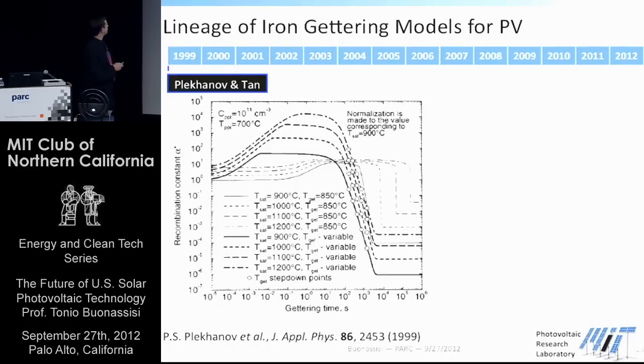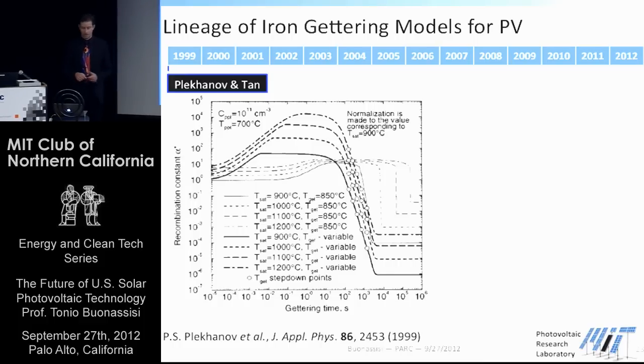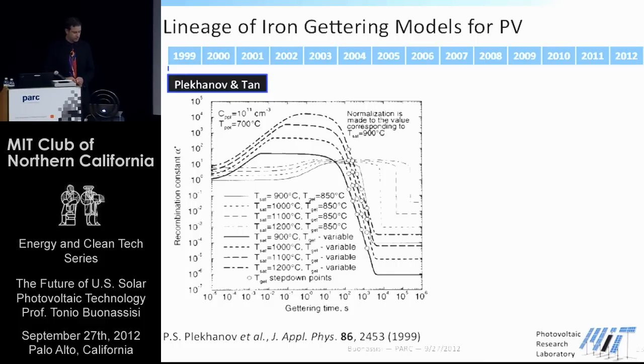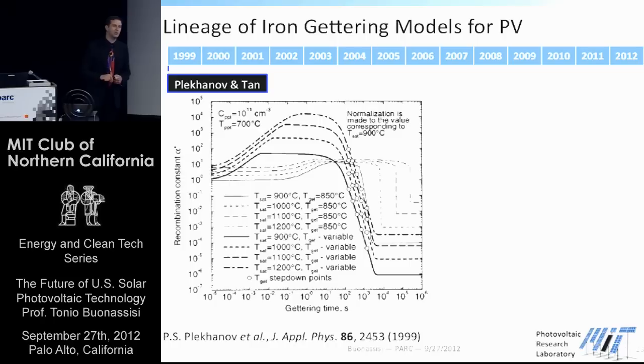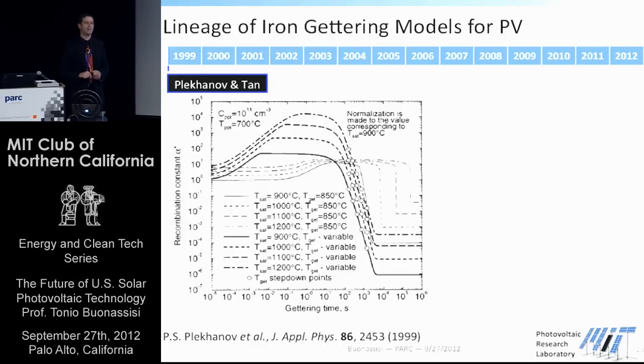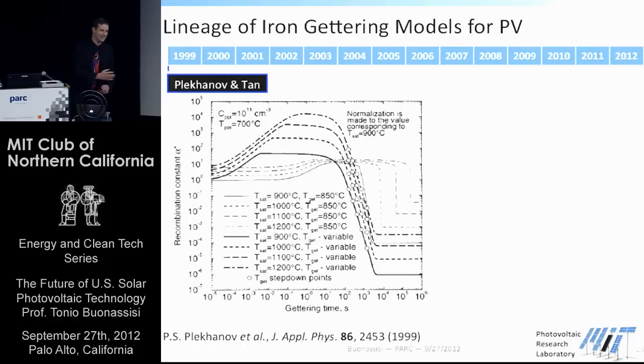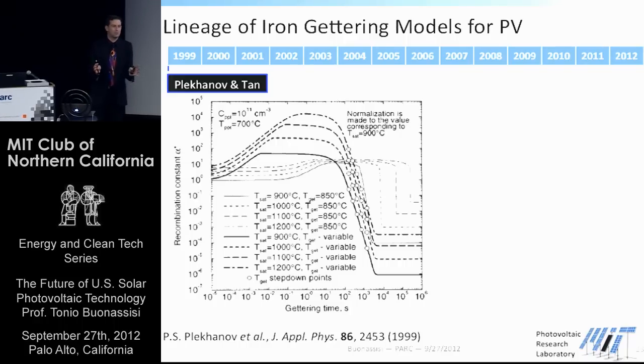Back in 1999, a group at Duke, Plekhanov and Tan, described for the first time some high temperature steps to dissolve precipitates and then different cooling profiles to getter them. These were simple models, but nevertheless very powerful and well ahead of their time. They got laughed out of the room because nobody believed that there were that high metal concentrations inside of solar cells. They said, well, integrated circuits have metal concentrations around 10 to the 10 atoms per cubic centimeter. How can you be modeling 10 to the 14, 10 to the 15? That's five orders of magnitude more than integrated circuit chips can have. No way are you modeling anything remotely representative of the real world.